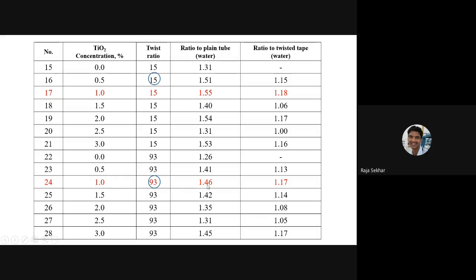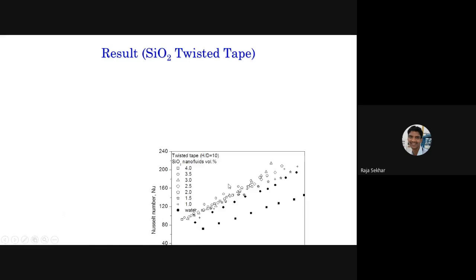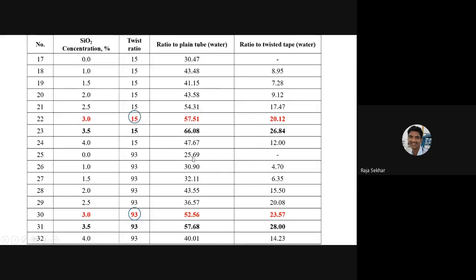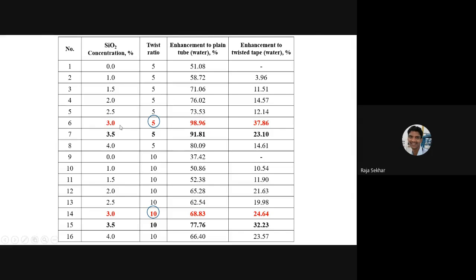So for that 1% only you are getting the highest enhancement ratios. Similarly for SiO2 we have seen that 3% is good. So the same is shown in this table. For 3% only you are getting the highest enhancement ratio. That means in the actual application also, the 3% SiO2 is giving you better enhancements.